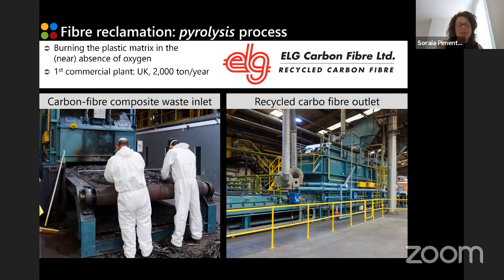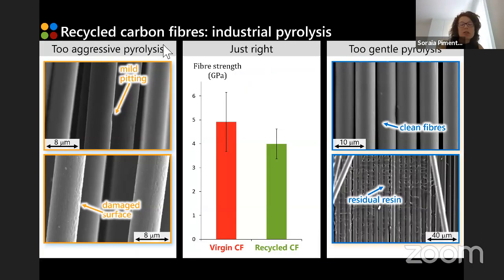I also think that there will be a presentation tomorrow from this company with more detail about the pyrolysis process itself. But basically, I just wanted to highlight that if your pyrolysis process is too aggressive, then you get damage on the fibers. If your pyrolysis process is too gentle, then you get some residual resin still holding the fibers together in bundles. And if you get your pyrolysis process just right, you get clean fibers with very similar properties to the ones that you have for the virgin composites.